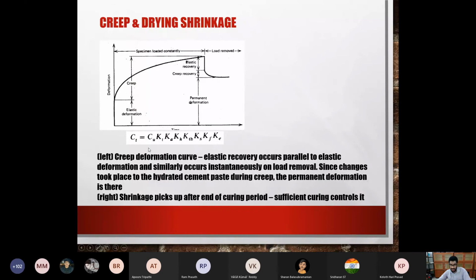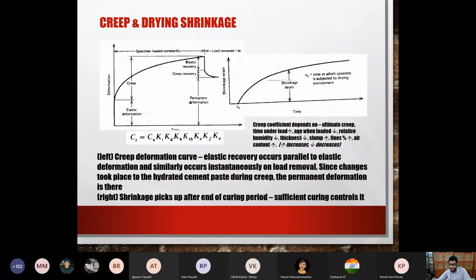It depends on several things like time under the load, age when it's loaded, relative humidity, thickness, slump, percentage of the fines, air content. It depends on all these things. And shrinkage happens because of your water cement ratio. And in order to control it, you do sufficient curing.